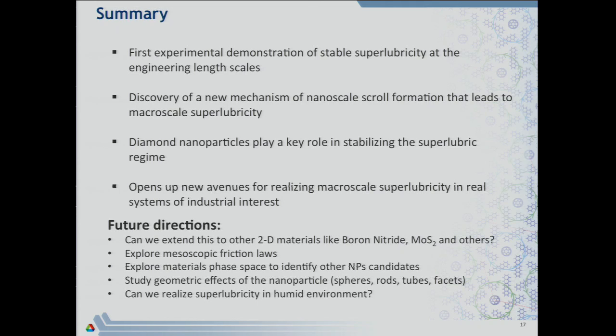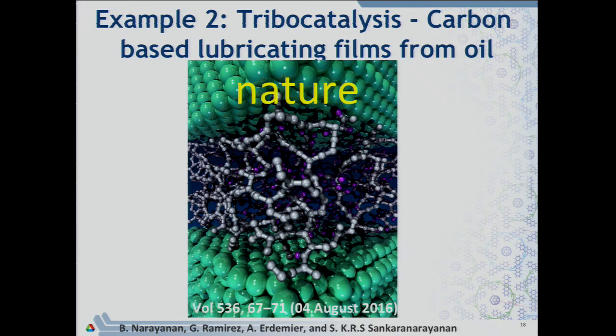We can explore the mesoscopic friction law — there are laws at the nanoscale and empirical relations at the macroscale, but nobody really understands how these translate from nanoscale to macroscale. That is an area of interest where ensembles of nanoparticles help bridge the gap. One important caveat: this superlubricity is extremely sensitive to humidity. If you have water, it prevents formation of scrolls and suppresses the superlubricity — which is why we're not yet seeing practical application.